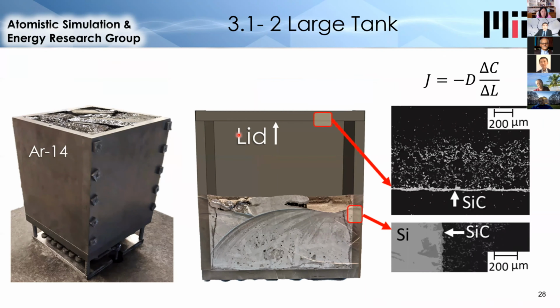And this is because the vapor pressure of silicon is relatively significant at these temperatures, just a few pascals, and the diffusion path to these surfaces is relatively short. So silicon actually evaporated and deposited on these other surfaces, reacting and forming a silicon carbide protective layer on all of these exposed surfaces.